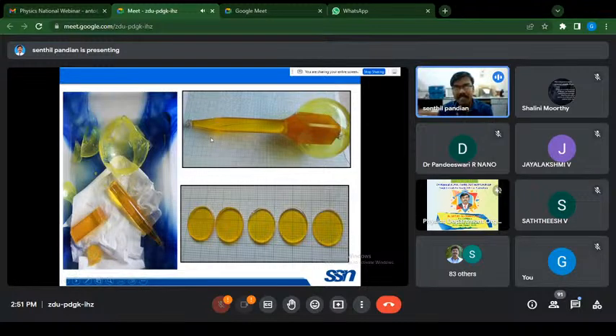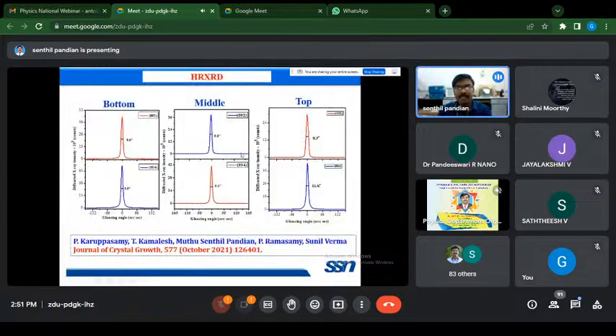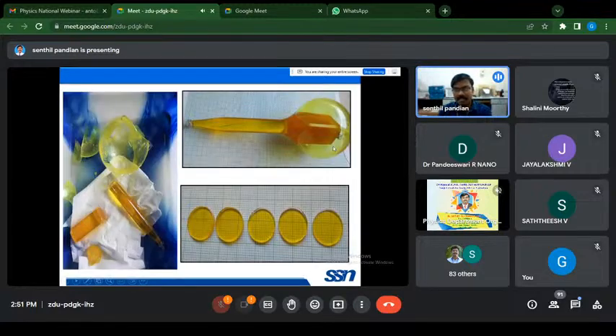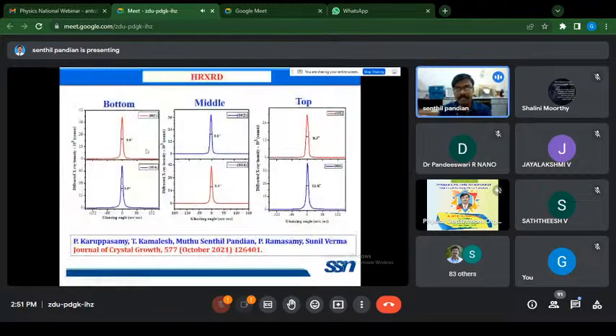In order to identify the crystalline perfection at the top, middle, and bottom portions, we have carried out the HRXRD measurement. The crystalline perfection of this grown crystal at the top, middle, and bottom portions is more or less equal.